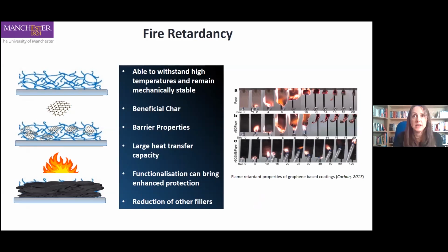The image on the right here I've just included because it's quite compelling. It shows if you use reduced graphene oxide and then reduced graphene oxide in conjunction with another material. It's actually sodium metaborate, and you can see that over time, as you put a flame to the material, you keep the material intact. Basically, this one goes up to 2 minutes, and you've got no effect pretty much on your graphene. So this is just dip coated paper. All the references for these are at the end, so anything you want to read in detail, you can go through them afterwards.